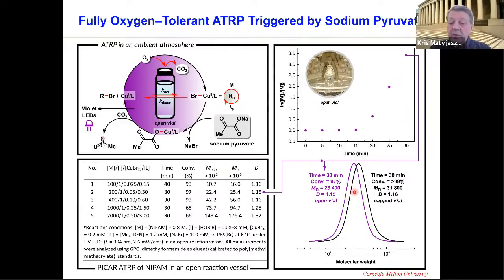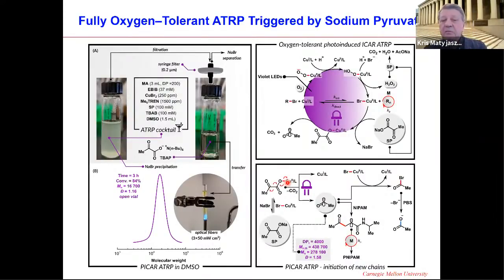And you could see whether it is capped vial or open vial, within 30 minutes, you get 97 or 99% conversion, low dispersity, good control of molar masses and dispersities. So this is a very good system for water, but sodium pyruvate is very poorly soluble in organic solvents.